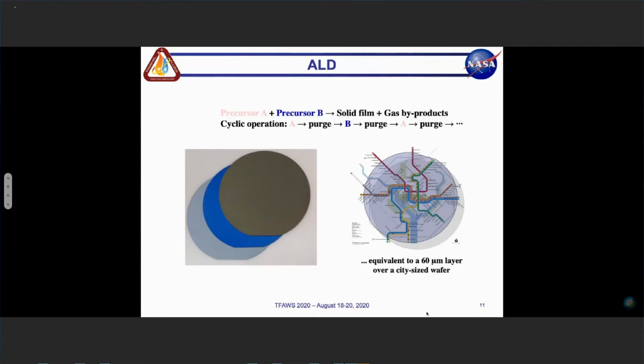Regular vacuum is good. Some of the great things about atomic layer deposition is the idea of uniformity. In equation form, you have one of the gases plus a second gas, precursor A plus precursor B gives you a solid film. And cyclically speaking, the way it works, you introduce your A precursor, you create a purge, and you introduce a B precursor, you create a purge. And you continue down this process until you get your material.